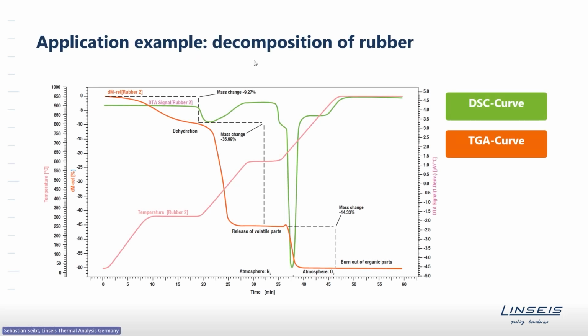On the next slides, there are some typical applications. This one is the decomposition of rubber. I show this in every STA presentation because it's quite a useful slide. What you see here is that the temperature was raised stepwise to 3 plateaus. After the first step, there's an initial mass loss. The orange curve shows you the mass loss again. So you see a loss of volatiles, you see a loss of humidity in the first segment in inert atmosphere.